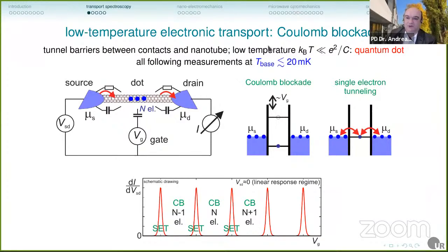And then what occurs is so-called Coulomb blockade. A current through the system is a priori blocked because there is not enough energy available for one electron to enter the system to charge this local system with one elementary charge. Only for very specific values of the electrostatic potential, an electron from the Fermi edge of metallic contacts can enter the system and then can tunnel out onto a free state at the Fermi edge again. And as a function of a gate voltage that tunes this potential, you then get these characteristic Coulomb blockade oscillations of the conductance. In the regions between the conductance peaks, the number of trapped electrons on the nanotube is fixed. On the conductance peaks, it can fluctuate by 1, and current can be carried via single electron tunneling. And when you tune the gate voltage, you charge your system with 1 electron after the other.